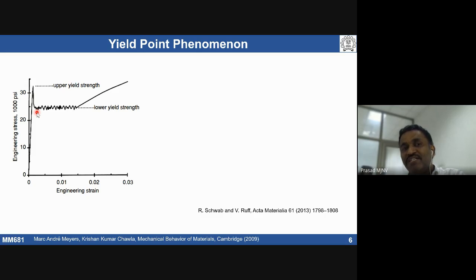Is it clear? Locking and unlocking are two activities which contribute to the upper yield and lower yield in the material. After that, once you unlock them, because you have solute atoms separately and dislocations are mobile, they can move very freely. So that can lead to some instability in the deformation. We are going to see some unstable plastic deformation.